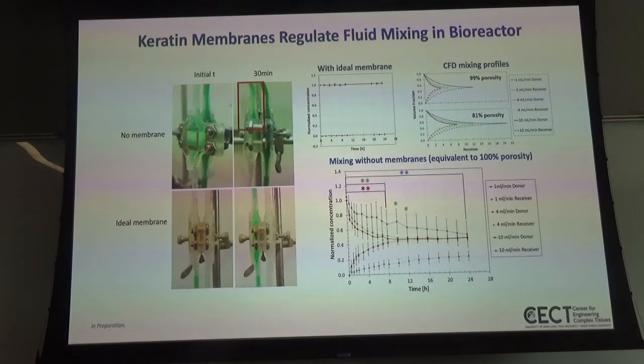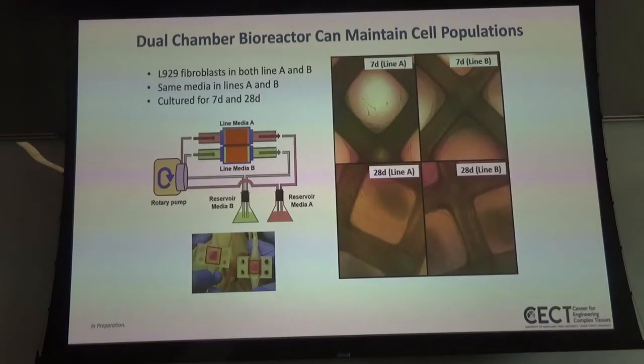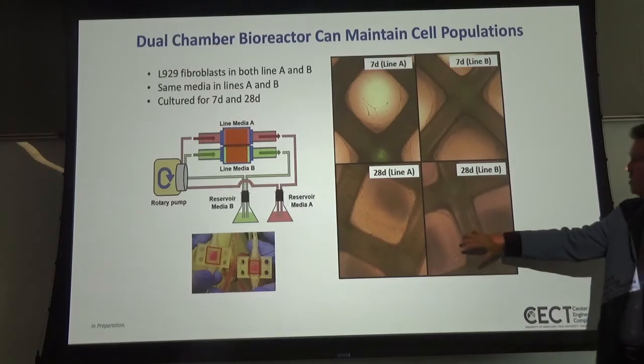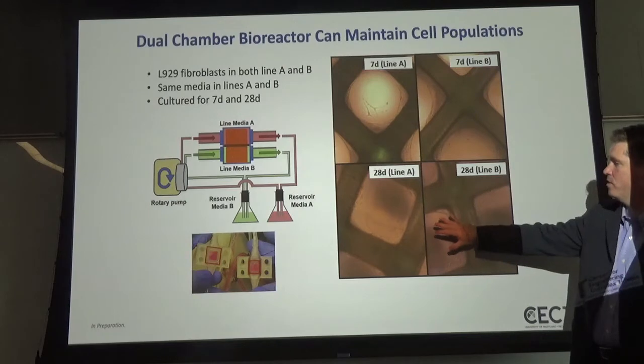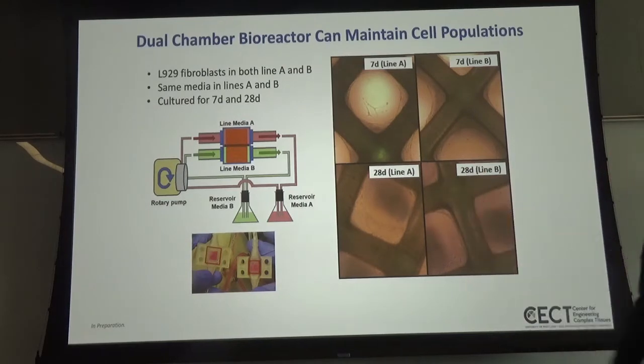Finally, getting to the real experimental work, the first test was taking fibroblasts, putting them in both chambers, the upper and lower chamber, so chamber A and B, the same kind of media, and then growing them over time and demonstrating that we get good, healthy, robust fibroblast proliferation and matrix expression in the two chambers throughout a 28-day study.